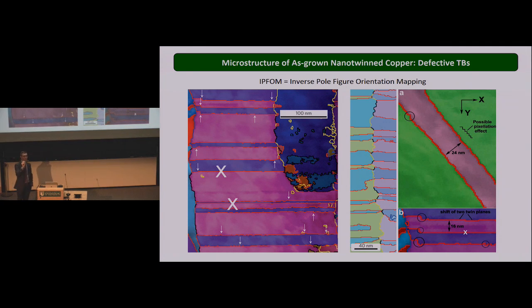But from each pixel, we get exactly the crystal orientation at below nanoscale resolution. And by using this special technique, we found that these perfect twin boundaries are actually not that perfect. They do contain tiny defects that look like tiny steps and that are far bigger than the resolution of the image here. They can be on the order of 1 to 3 nanometers. So it totally redefines the way we think of the nanotwin materials and the twin boundaries as perfect coherent boundaries. They actually are defective interfaces on the very nanoscale.